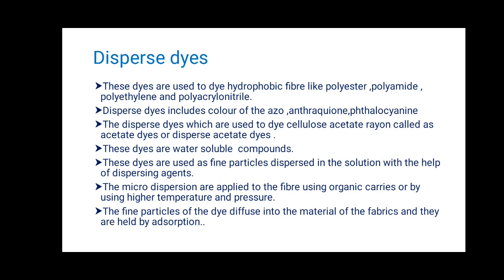The micro dispersion is applied to the fiber using an organic carrier or by using a higher temperature and pressure. The fine particles of the dye diffuse into the material of the fabric and are held by adsorption.